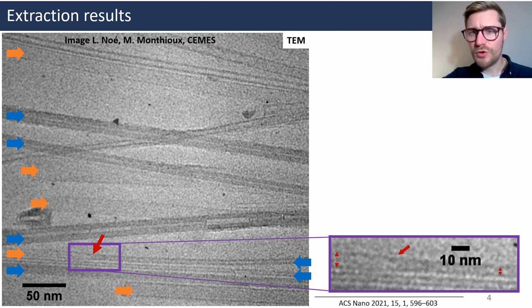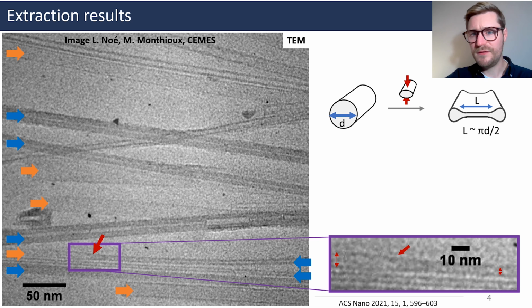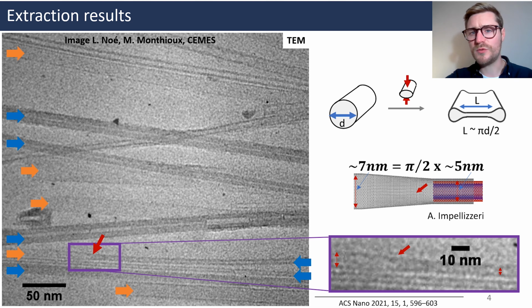The tube shown here by the red arrow is quite interesting. It's cylindrical on one side and collapsed on the other side. To be sure that it's really flattening and not unzipping of the tubes, which does happen, we compared the widths on both sides. If you collapse a cylinder into a ribbon, the width of the ribbon should be π over 2 multiplied by the diameter of the initial cylinder. This is what we found here.